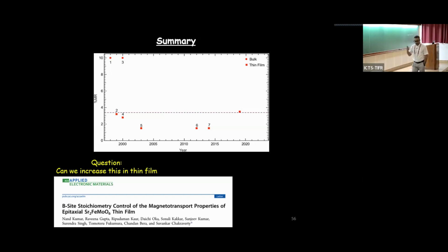So what we have done, as I said, is that in pulsed laser deposition, you have two knobs. One is thermodynamics and another is kinetics. People have so far tried with the thermodynamics. We wanted to try with the kinetics. That is, change the laser fluence and see what happens.